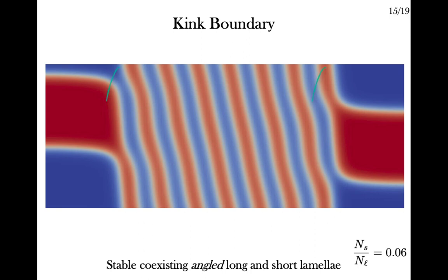We don't know a priori how much copolymer goes to the interface or the interfacial width, meaning that we can't precisely calculate the relationship between the amount of copolymer in the system and the size of the domains, making it impossible to line up the long and short lamellae appropriately. When one doesn't know how much polymer to use, the usual thing to do is to use the grand canonical ensemble and let the system decide. However, if we do this, the system would simply convert into one containing only long or only short lamellae in order to get rid of the interface. We don't know how to set up the system to ensure that the short lamellar spacing and the interface are both at their equilibrium values.